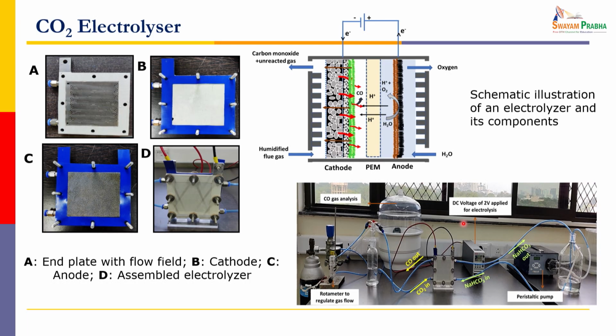This is a cell of about 6 by 6 centimeters, a 36 square centimeter cell we have developed. Earlier it was just an experiment where you pass CO2 and analyze one by one, more of a batch reactor. Here we wanted to continuously feed the CO2. This is a continuous reactor. You continuously pass CO2 and you should be able to get formic acid continuously. This is ongoing work, and hopefully another time we will have some data from such an experiment, but it's ongoing work as of now.